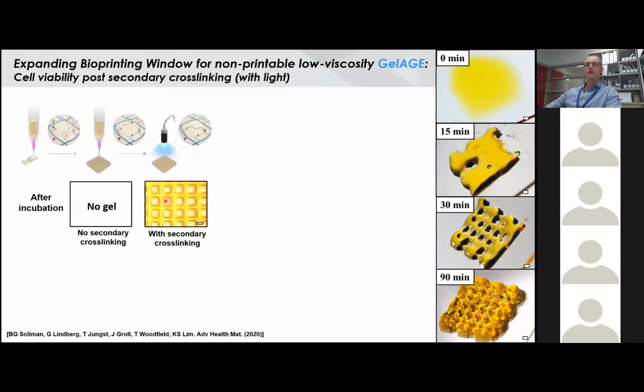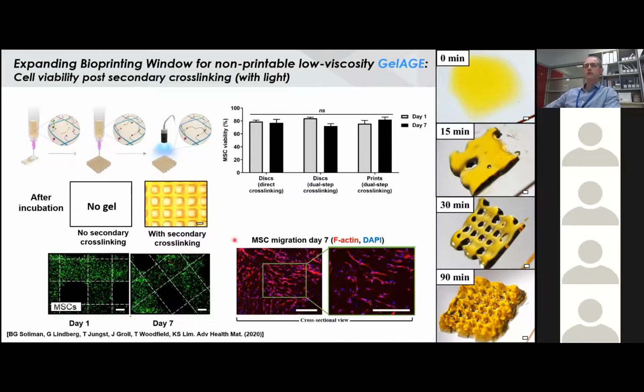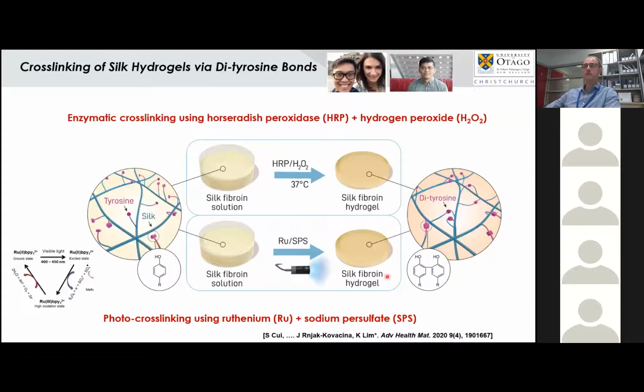But if you take your essentially primary cross-linked construct, and then you do a secondary cross-linking step, this time with light, using again the ruthenium SPS, then you can end up with very stable constructs, where we see in our hands nice cell viability and starting to see migration of mesenchymal stromal cells. So again, this is an interesting way of harnessing the capability of the photoinitiator system.